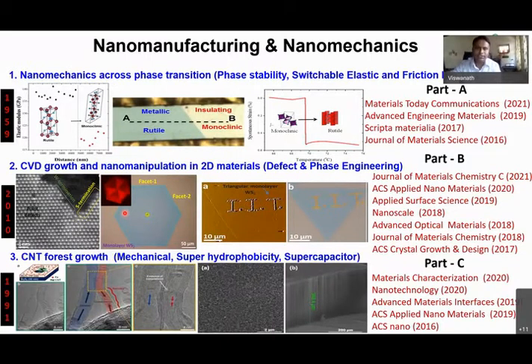This kind of phase coexistence and phase manipulation has to do with the strain and also defects and substrate interaction and so on. We have some results. I will see whether I can at least initiate. We also use nano indentation for sculpting, like lithography. We can use nano indentation to induce local strain, and in extreme cases, it is possible to remove the material by selectively doing indentation. What you have seen here is essentially the nano sculpted area wherein we can remove the 2D materials, in this case, WS2 monolayers.